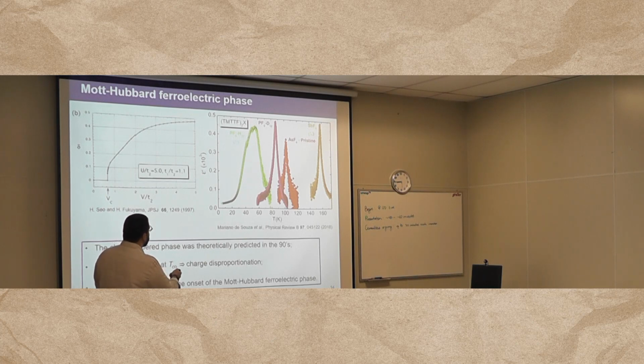So this has been done in the past for the various salts. We have a symmetry breaking at the charge order phase transition because of the charge disproportionation. And since this is a Mott insulator, explained by the Hubbard Hamiltonian, and it presents a ferroelectric phase, we have called this the Mott-Hubbard ferroelectric phase. So we are interested to see if this particular phase is magnetoelectric or multiferroic.